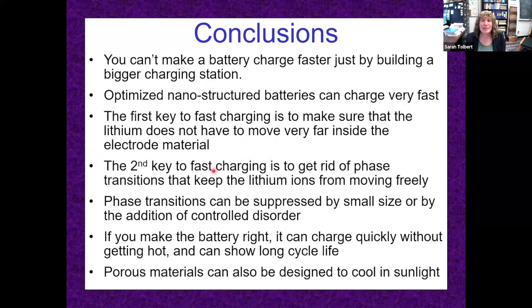And the second key is to get rid of those phase transitions that keep the lithium ions from moving freely into and out of the material. We can get rid of those phase transitions either with small size or by adding disorder to our material. And if you make your battery right, it can charge really quickly without getting hot, and it can also show very long cycle life. And then finally, at the end, I gave you just a little teaser on porous materials for daytime radiative cooling, that we can actually create materials that we can put in the bright Southern California sun and have them get spontaneously cooler.